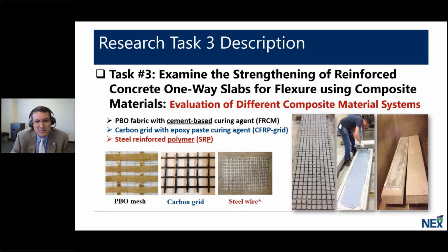So these 3 systems that we looked at and compared were first the PBO fabric that we looked at in shear and flexure and fatigue. Number 2 is a carbon grid with epoxy paste curing agent. So here we're comparing a one-way slab with a cementitious, but a different fiber with an epoxy paste curing agent. And then 3 is a steel reinforced polymer. And it's important to note these are galvanized high strength steel wires.